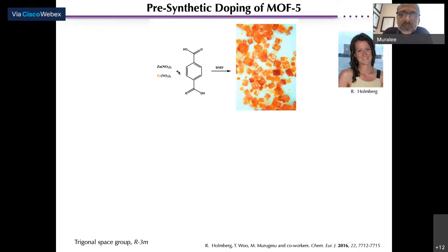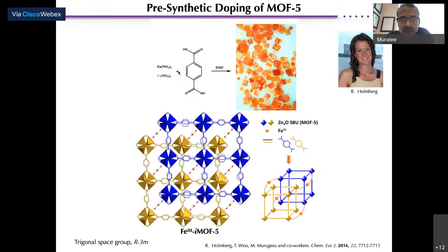So it's almost like a dilution type methodology, where we were able to get these beautiful cubic orange crystals, which is reminiscent of MOF5, and the structure clearly shows an interpenetrated MOF5 system. We know that MOF5 can also crystallize in an interpenetrated framework, but now you can see this interpenetrated framework is linked by these orange balls, which represent the iron, and the two oxygen atoms which are linking these interpenetrated frameworks.